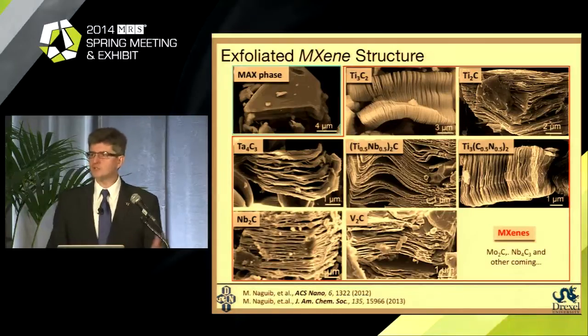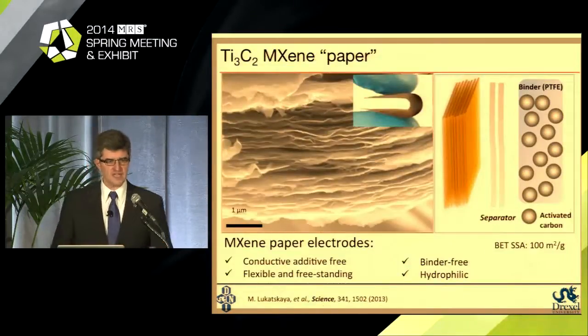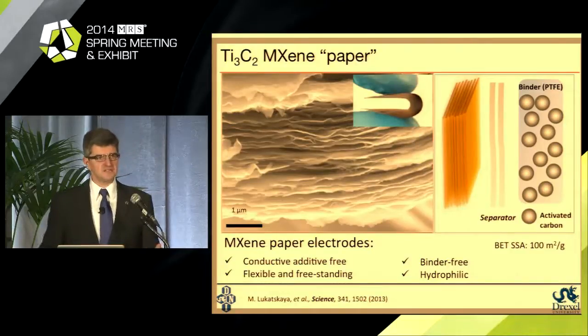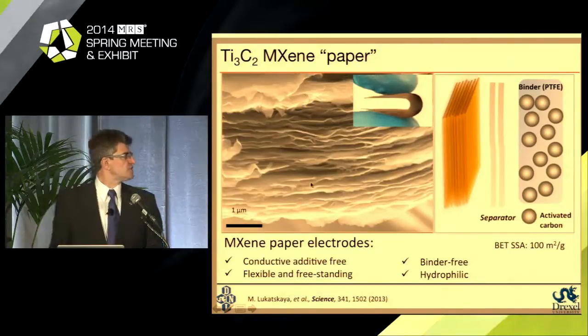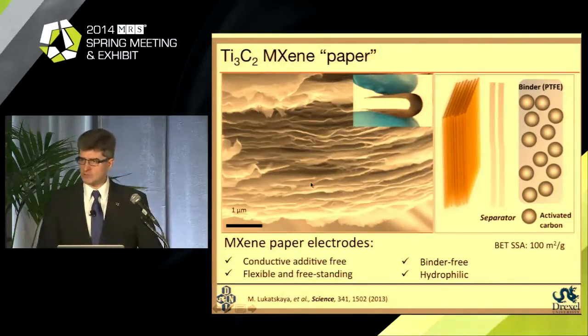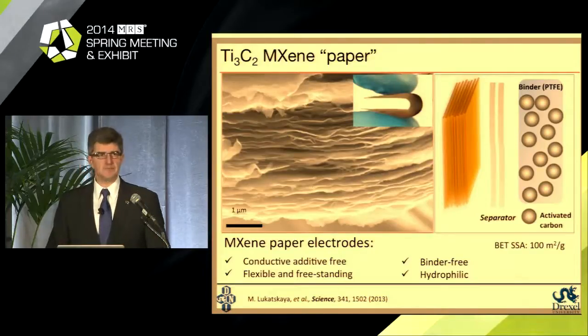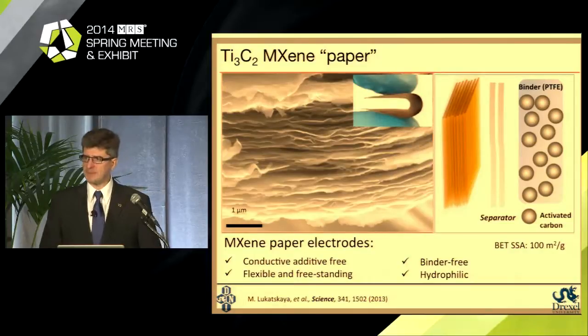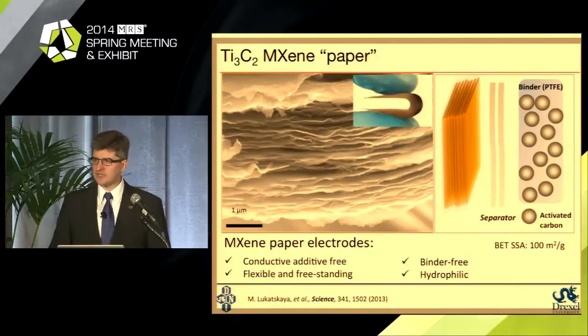So we really have a totally new family of two-dimensional materials, and again, they can be produced in single flakes. You can filter a colloidal solution and make MXene paper just like you make graphene paper. Also, DFT calculations and experimental measurements showed they have a metallic character of conductivity. Also, surface termination can open the band gap from less than 0.1 electron volt to 2 electron volt, depending on the composition of these materials. So we can make, again, conducting, very strong and thin materials.